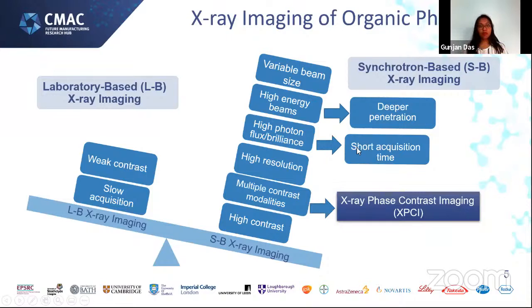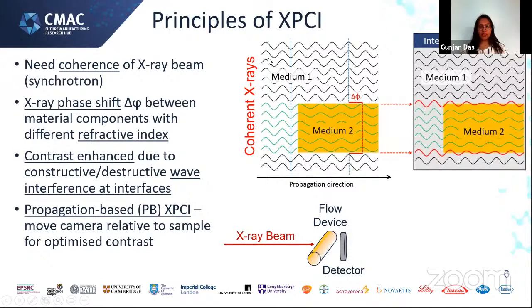Now the principle of how XPCI works. As you can see, you need coherent X-rays, and that is only available at the synchrotron facilities. For this technique to work, every material has a variable refractive index. Upon interaction between the sample and the X-ray beam, there is a phase shift that's being introduced, causing an enhanced contrast, which is also caused by constructive or destructive wave interferences at the interfaces. The technique we have used is propagation-based XPCI, where the camera is moved to different distances compared to the sample for an optimized contrast.